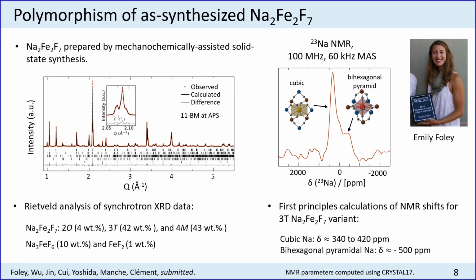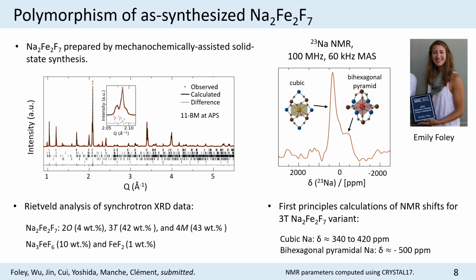So we also looked at this material with NMR. This is really the expertise of my group, using solid state NMR to characterize battery materials and to understand their mechanism. This is a spectrum obtained on this material using sodium as the probe. Here we're probing the local structure around these sodium nuclei in the material.